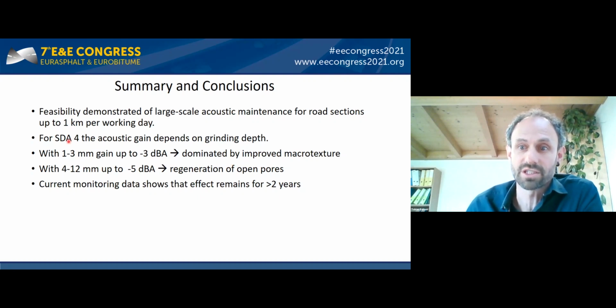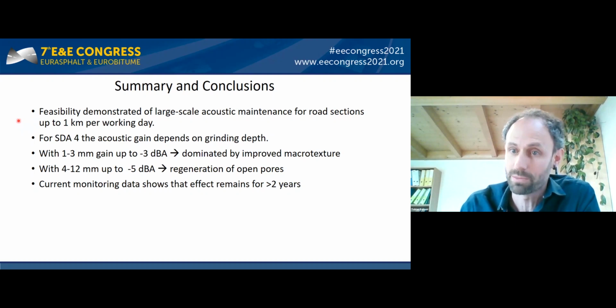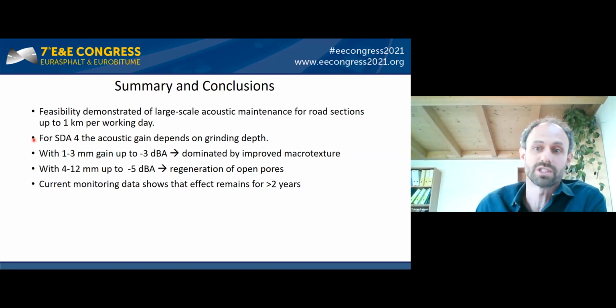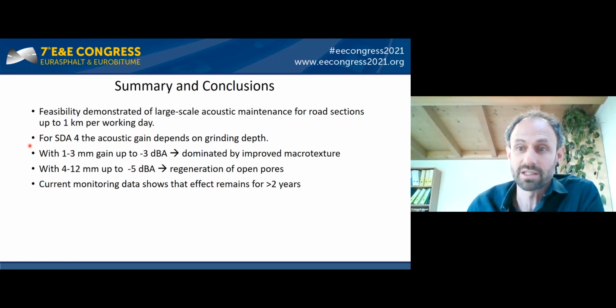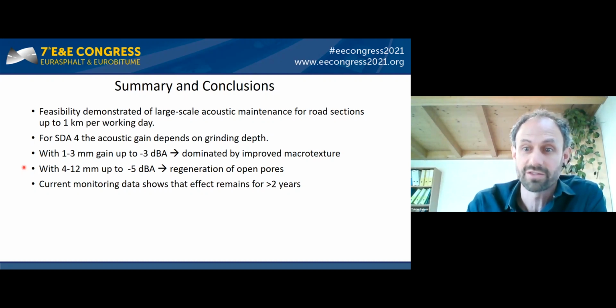I showed you that large-scale grinding for acoustic maintenance of aged road sections of up to 1 km per working day is feasible. For SDA 4, the acoustic gain depends on grinding depth. With little grinding of 1 to 3 mm, we already obtained 3 dB. This effect is dominated by improved macro texture. With larger grinding depth in the range of 4 to 12 mm, we gained up to 5 dB. And the additional effect is due to regeneration of open pores.